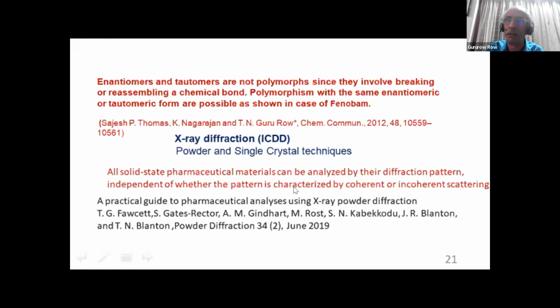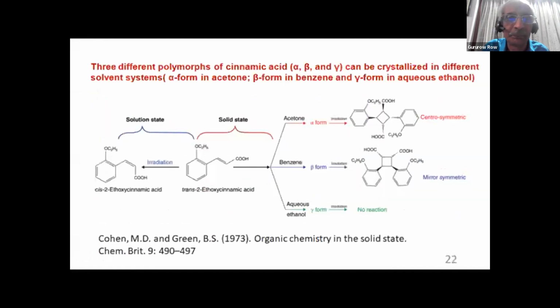This covers all forms of solids, which means crystalline and non-crystalline. And that's the reason why they are saying coherent or incoherent scattering. Incoherent scattering essentially is not something which is generally employed in a routine diffraction technique. In a routine diffraction technique, where we have the powder diffraction or the single crystal diffraction, we always use the coherent diffraction data. The X-rays are coherent in all these situations.